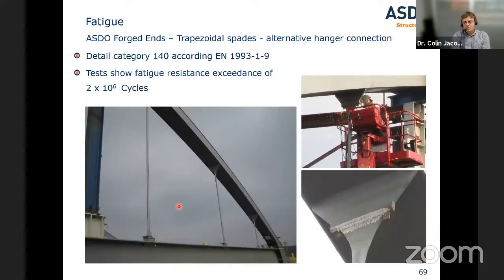I mentioned before that we also have provided forged ends. This is a system common in Germany, particularly for some of the infrastructure projects, where they prefer to see a welded detail. This detail category is actually 140, so very onerous, but we can still make this and get fatigue resistance in exceedance of 2 million cycles. So here you can see we forged the ends of the bar, we flatten out the area, allowing a nice horizontal full penetration weld to the two sides.